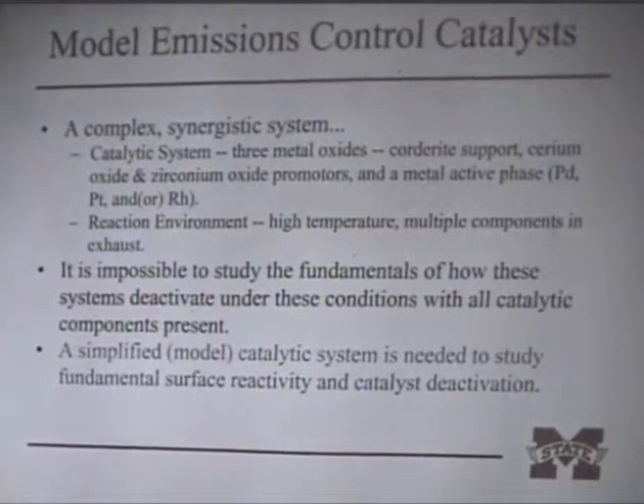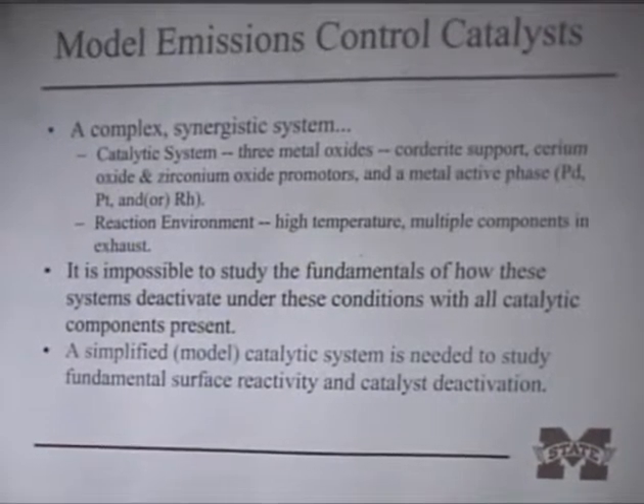So what have we got? If you're looking to model this, and by model I mean from an experimental point of view, we have a complex synergistic system. We typically have three metal oxides: a cordierite support, cerium and zirconium oxide promoters, and then a metal active phase, which can contain palladium, platinum, rhodium, or a mixture of different things. In our reaction environment, we can go up to 1,000 degrees K, which may not be that high a temperature, but we have multiple components in the exhaust.